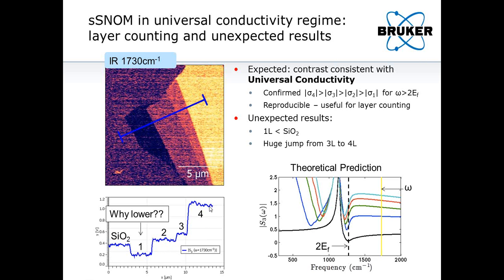There's a monotonic increase in signal as we go from 1 to 4, and we also see that this is very clear contrast. It's not a faint signal at all, it's very clear. And what's surprising here is that the first layer signal is a little bit lower than the SiO2.